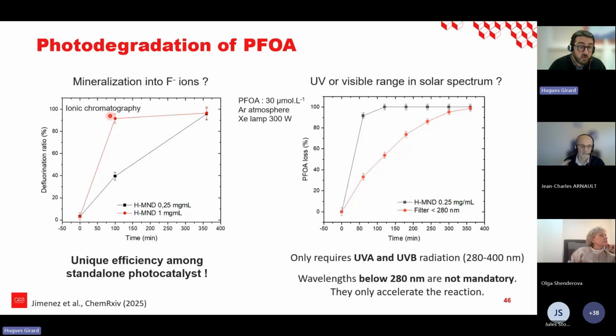This is ionic chromatography. And you can see that we can go up to almost 100% of fluorine. So it means that all the carbon-fluorine bonds were broken. And it happens quite fast, after only 100 minutes for the highly concentrated nanodiamond suspension. And also we had to look a little bit more closely at the wavelength responsible for the effect. And what we observed is that we only require UVA and UVB, so between 280 and 400 nanometers wavelength, to activate the phenomenon.